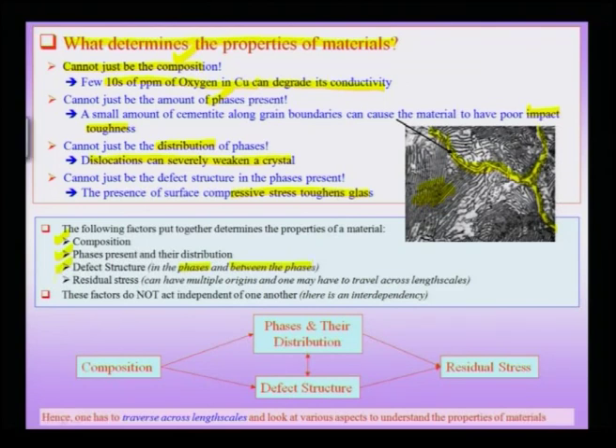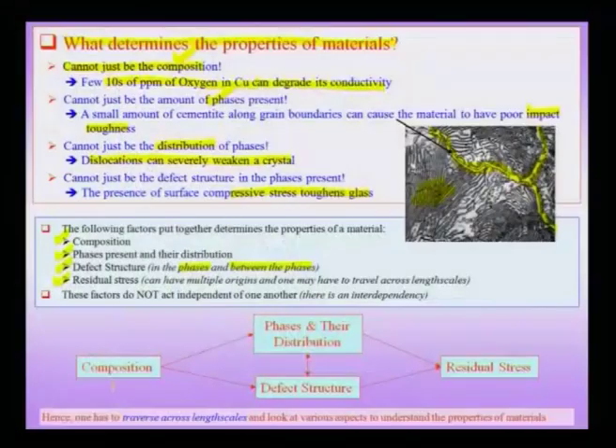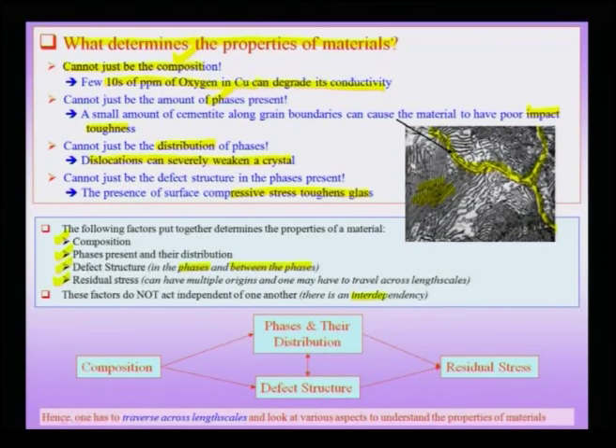Last but not least, I need to know the residual stress, and as we shall see later that residual stress can have multiple origins. To understand all these aspects, I not only need to know the phases present and their distribution, the defect structure and distribution, but also the residual stress and its distribution. And in doing so, I would realize that these factors are not independent of one another — they often talk to each other across length scales. For instance, a coherent precipitate is not only a defect in the perfect single crystal but also is associated with residual stresses, so the precipitate and the residual stress are intricately intermixed, and this interdependency often gives rise to the properties which one observes in a material.